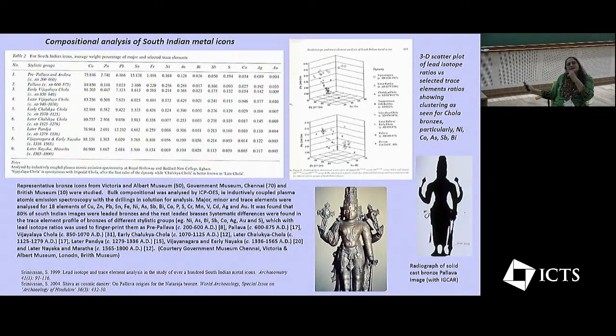But you see, in the case of the South Indian bronzes, what I found is there was some patterning based on the chalcophilic elements based on the ore sources. So there was some clustering across different groups of bronzes of different periods, which came from different ore sources, which also was reflected in the clustering of the trace elements, which in a way I could also use to tell apart bronzes of different periods. But it's also interesting that the gold-silver ratios also should show linearity, which reflects this pattern of being related to the ore sources, being chalcophilic. That should be normally the case. But in my South Indian bronzes, the gold-silver ratios were all over the place. And the reason for that is a very interesting reason.